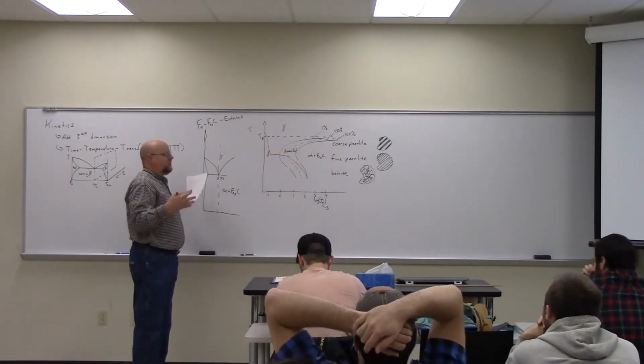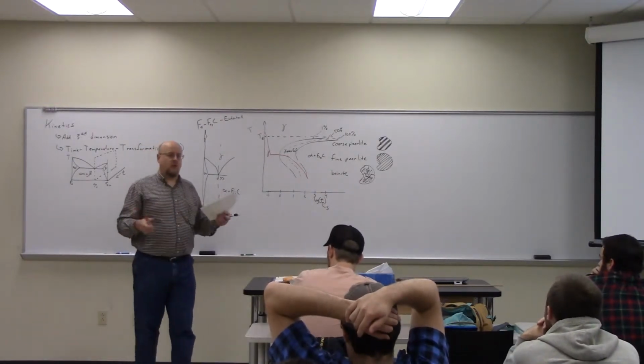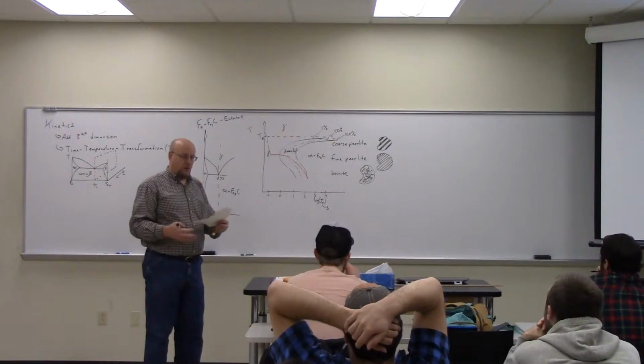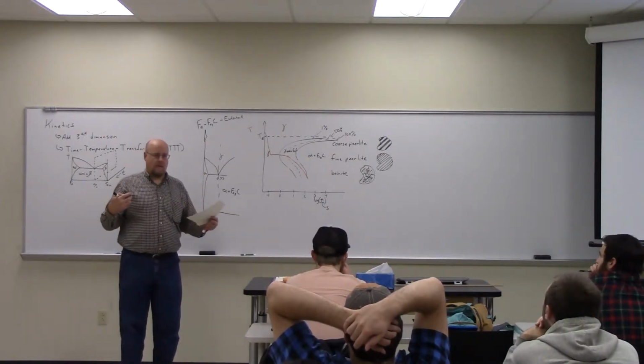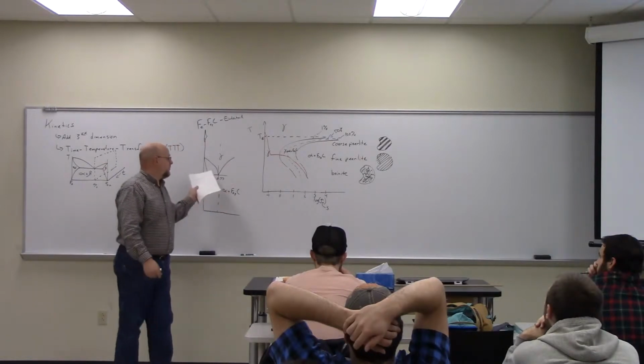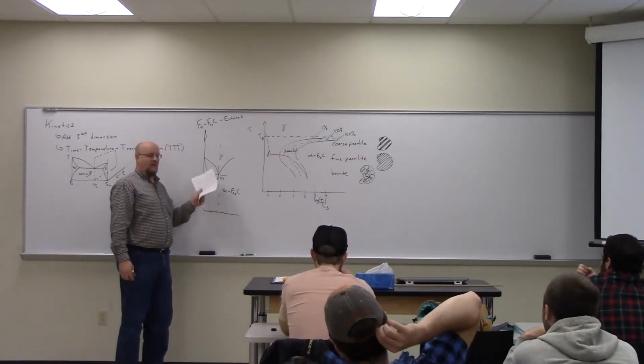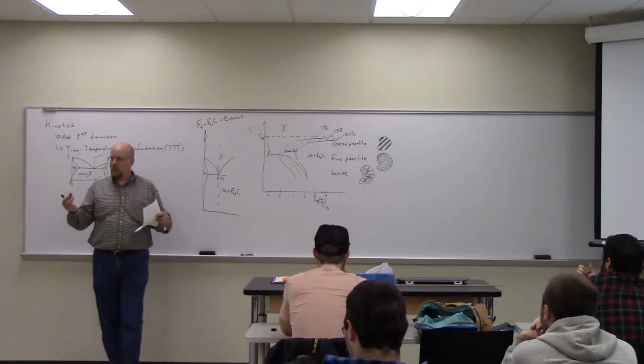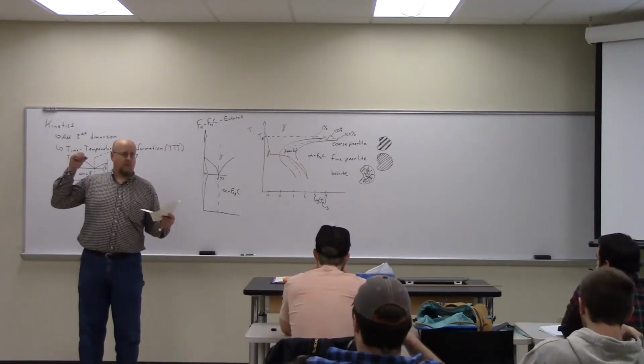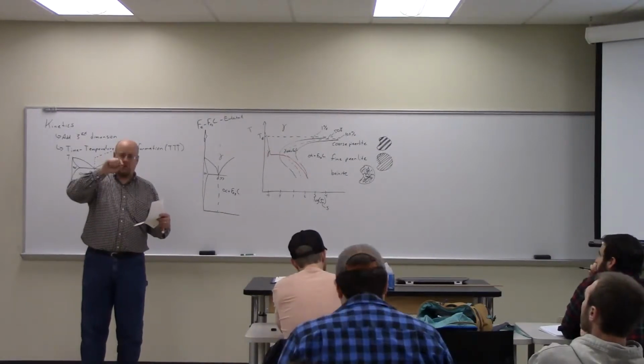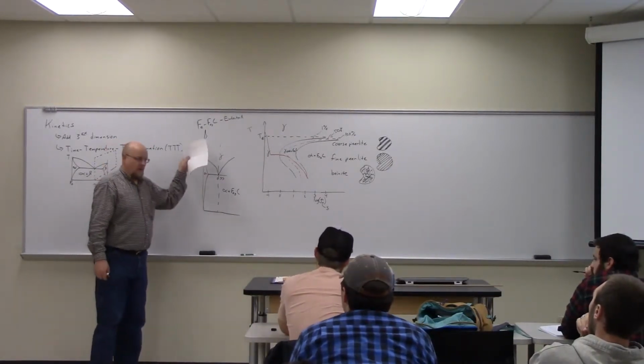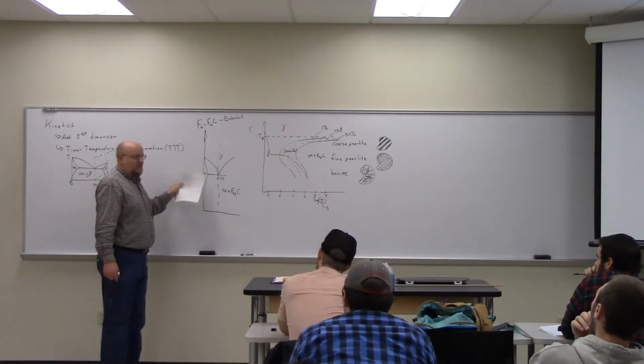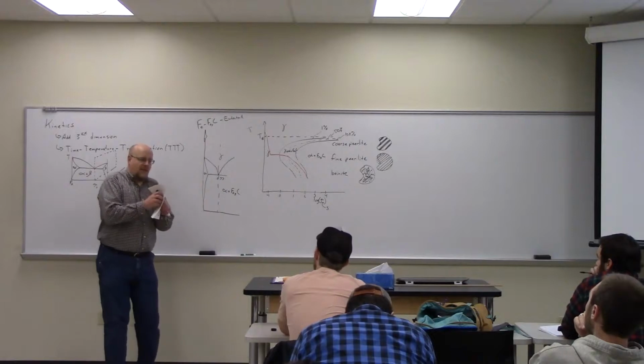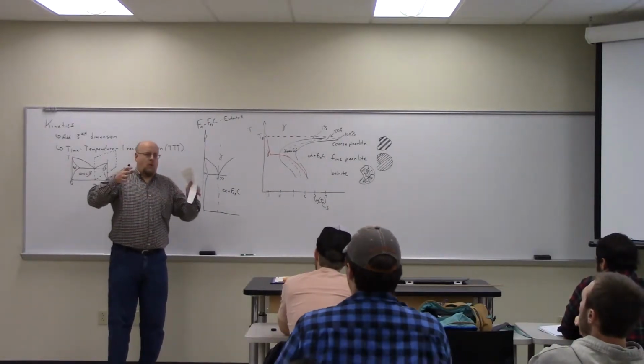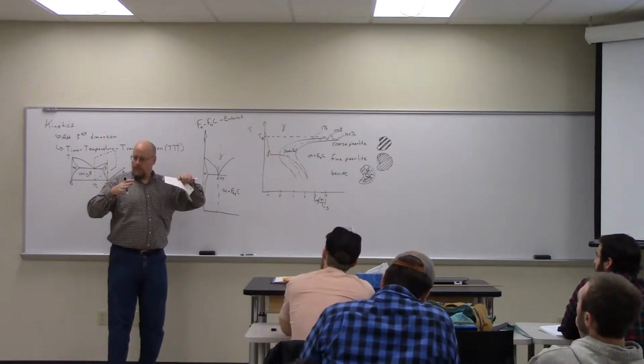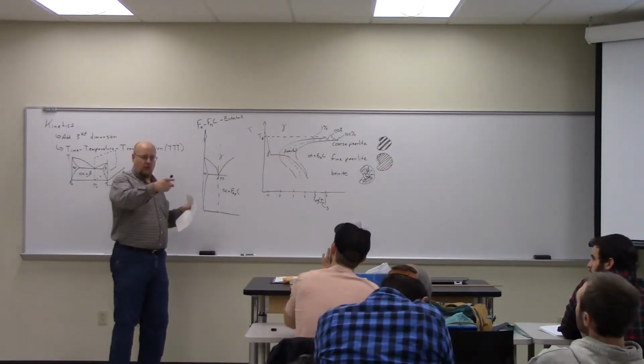Now the thing is, all of these phase transformations are based on a diffusion process. You have to diffuse a second phase out of a first phase. Even when the composition stays the same, I have to diffuse an alpha out of a gamma. Alpha will form at the grain boundaries, at the trifold intersections of the grain boundaries. If I take some gamma that has grain boundaries and then cool it, the alpha will begin to form at the intersections of the grain boundaries, and the alpha crystals will grow while the gamma crystals shrink. That's the way the process works. So it's a diffusion-driven process, yes?